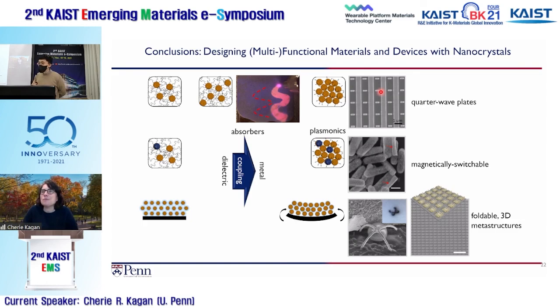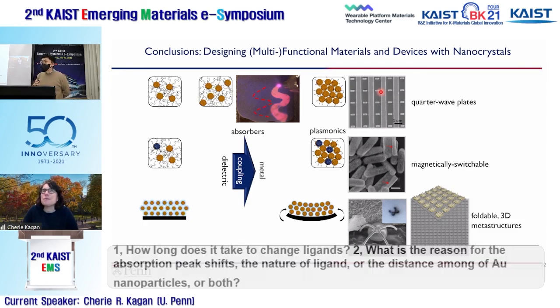Okay, I have two questions. So you can tune the transmittance of gold particles by ligands. First question, how long does it take to change the ligand? Second, what is the reason for the absorption peak shift: the nature of the ligand, or the distance among the gold nanoparticles, or both?